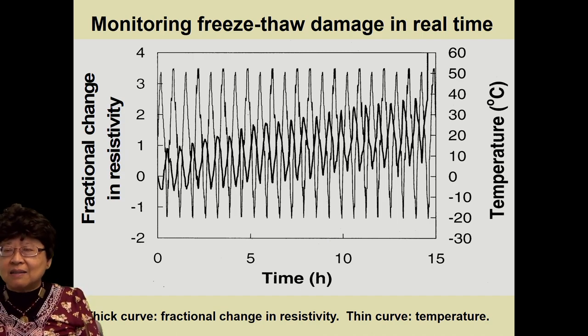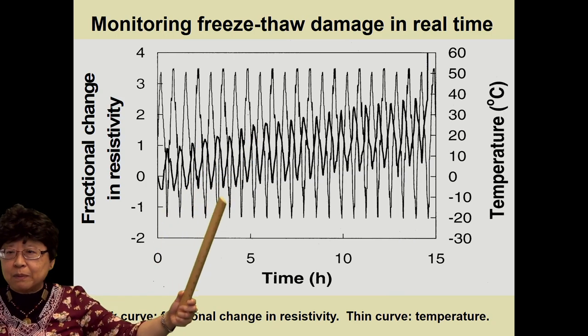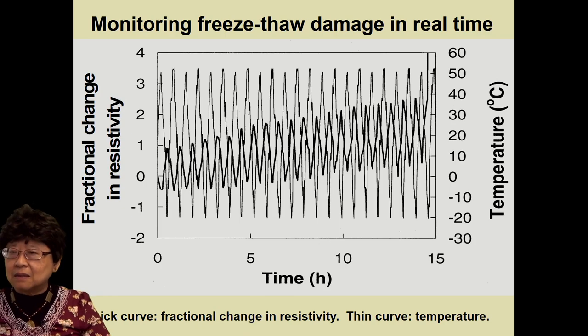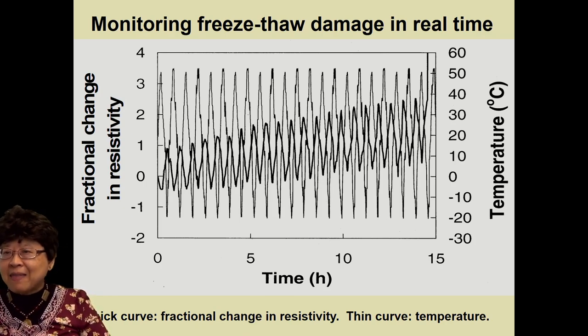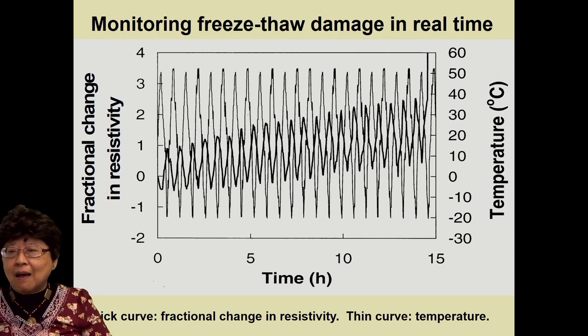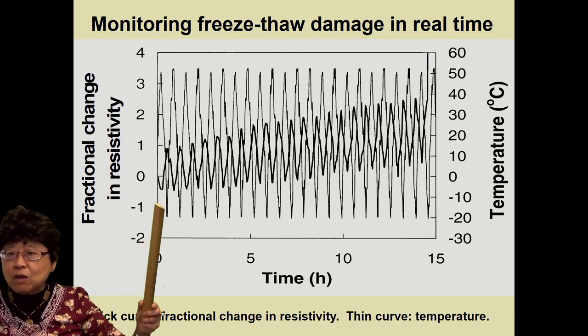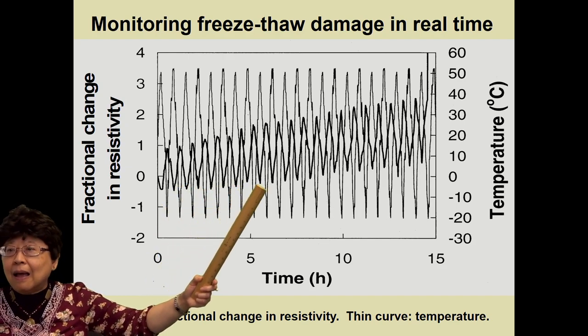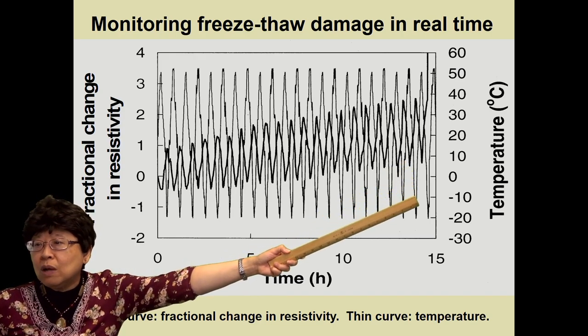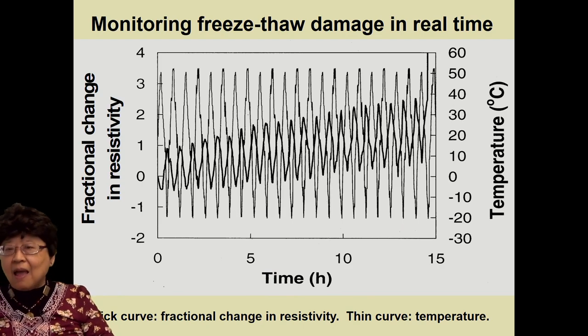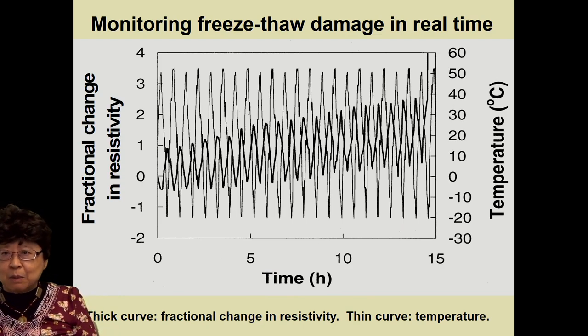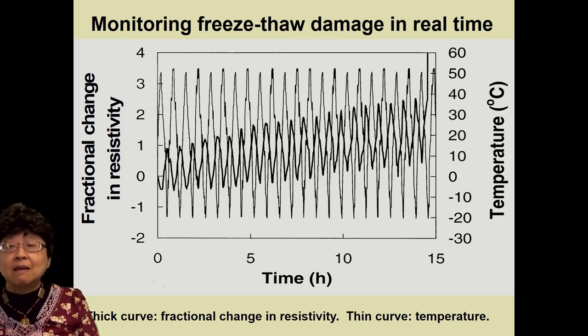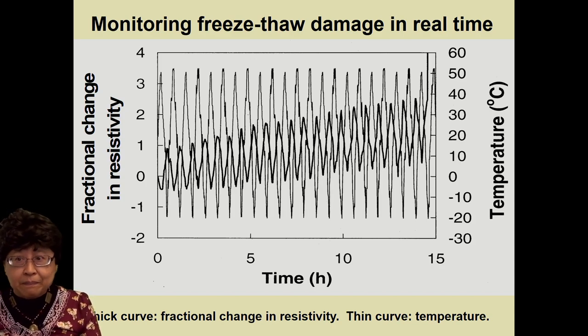But the interesting thing is that both the upper envelope and the lower envelope gradually increase cycle by cycle as the freeze-thaw cycling takes place. And that's an indication of damage. Damage almost always increases the resistance. And one sees that the damage occurs in every cycle incrementally. And it finally fractures at the coolest point of the last cycle. Okay? And this is the very first time that anybody has been able to monitor freeze-thaw damage in real time. And it's important to do this monitoring also for the sake of understanding the process of freeze-thaw cycling damage.